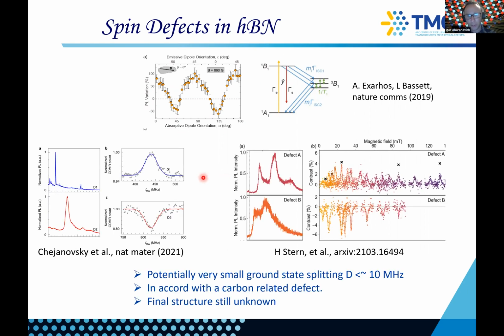And so earlier this year, the group of Jörg Wrachtrup, they actually found that a subset of these defects in the visible range, so they call them D1 and D2, actually exhibit ODMR. And remarkably here, some of them show positive ODMR and some of them show negative ODMR, and only at cryogenic temperatures. And so the group of Mete Atatüre, they actually expanded this work significantly, and they showed that actually most of these emitters also exhibit ODMR at room temperature.